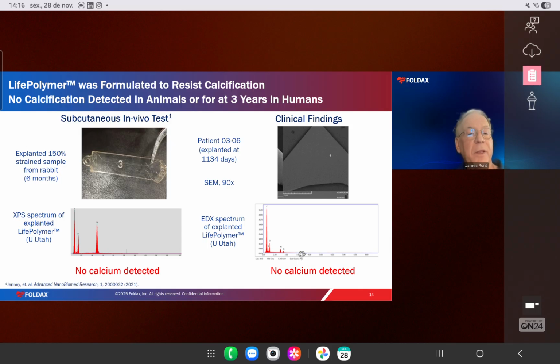This number, we see number 3 there. This is the pair of tweezers, and it's holding the sample after it's been explanted from the rabbit, and it's pristine, right? And what we did was we did X-ray photoelectron spectroscopy. Again, what that is not important, but we gently cleaned the surfaces to remove the biological material, and then used this characterization technique, which is basically characterizing the elemental composition of the material at the surface. And you can't see the details there, but there's no calcium detected at the surface.